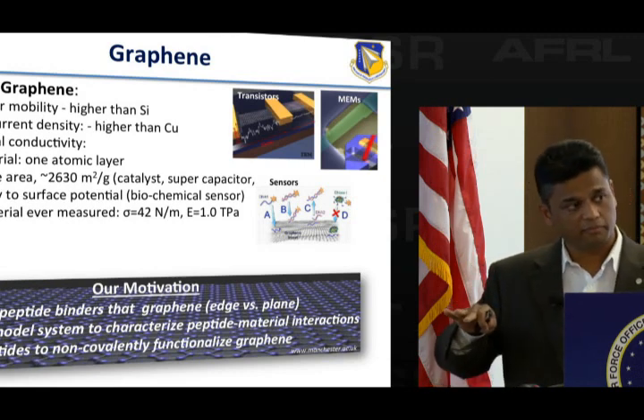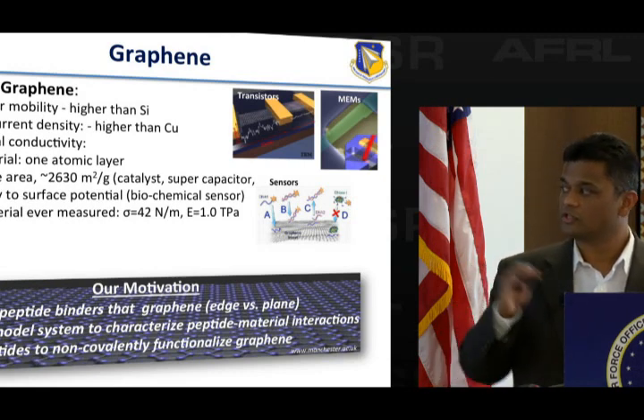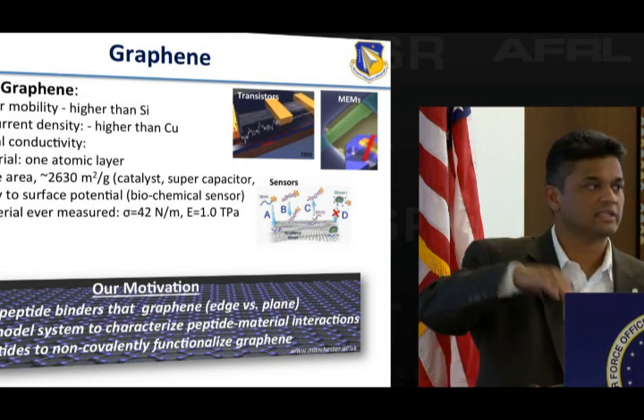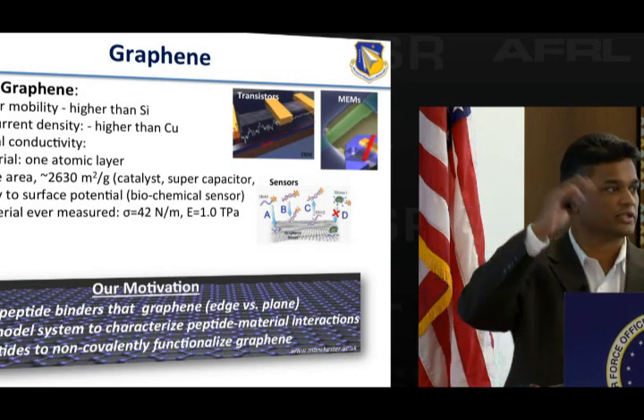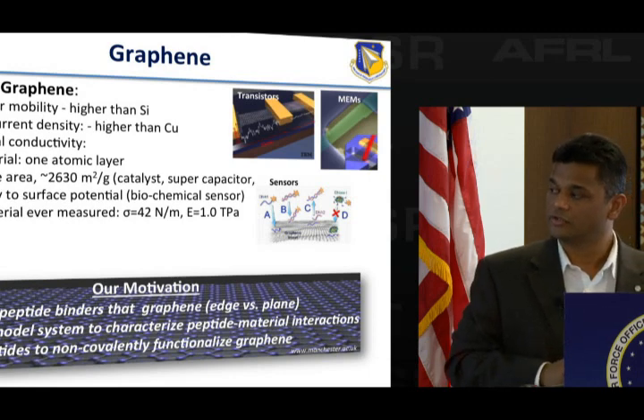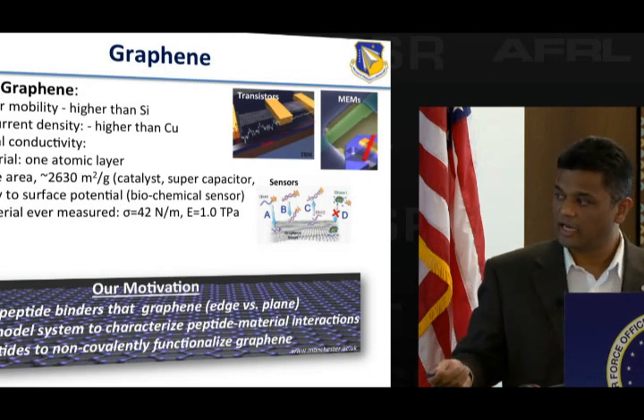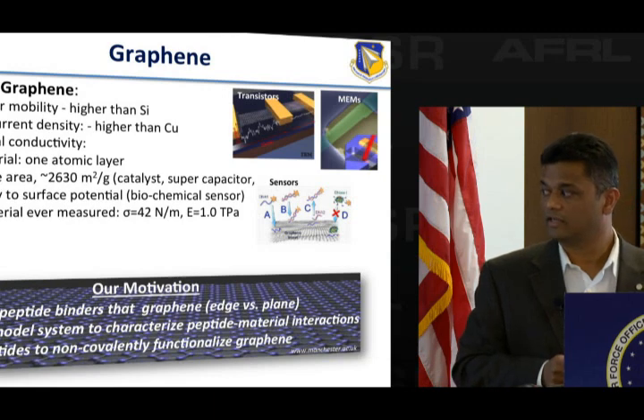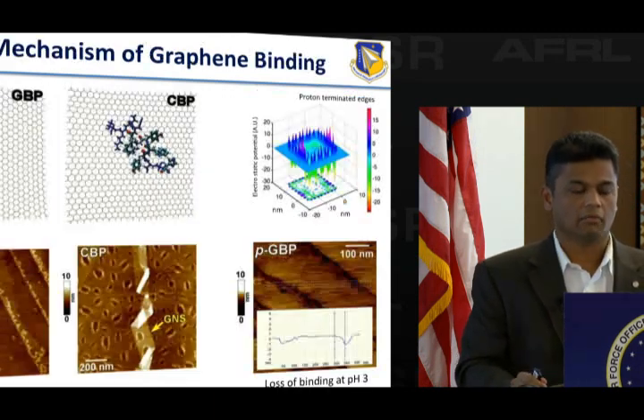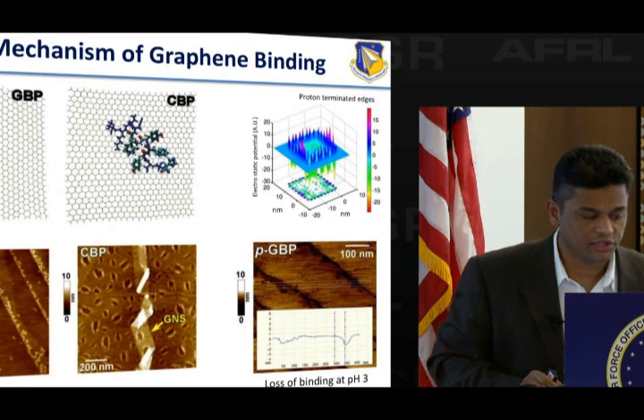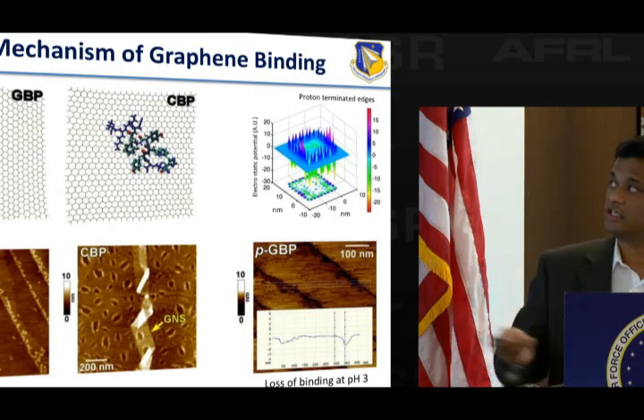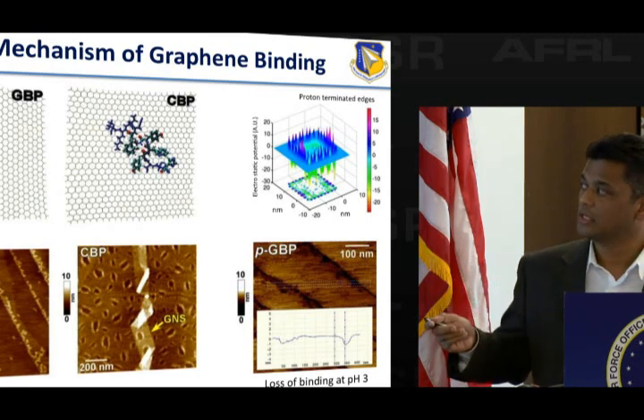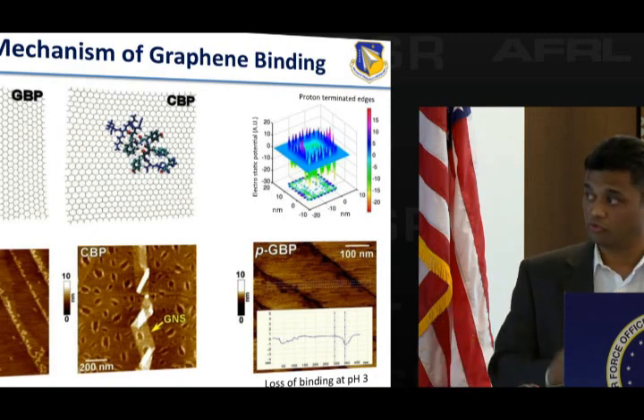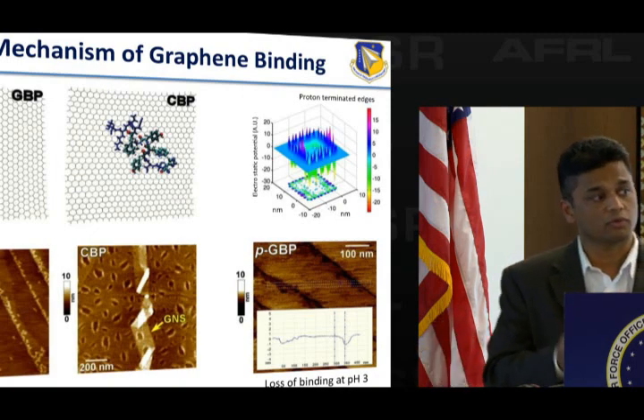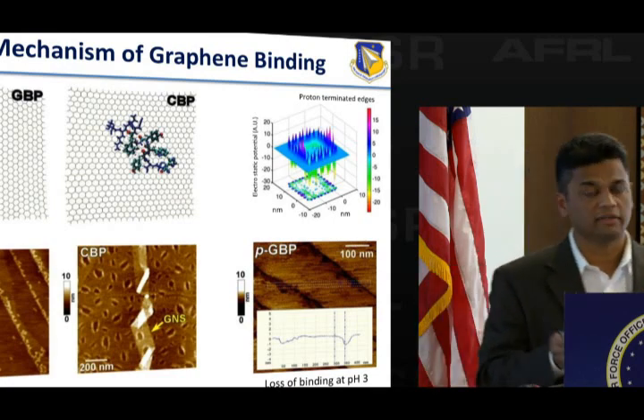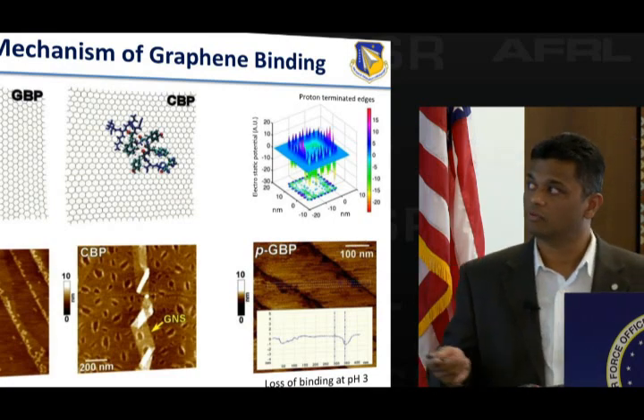And because this is a nice flat plane system, you can also look at whether you can characterize how these peptides interact with the material by doing force distance measurements, so you can see interaction energies using AFM-based techniques. And the idea is maybe you can use this to non-covalently functionalize graphene. We have done a lot of the characterization using FTIR-based methods, CD spectroscopy looking at protein structures, and Raman spectroscopy to make sure that we're not introducing any defects. So we see that we introduce very little or no defects when you non-covalently interact with the peptide.